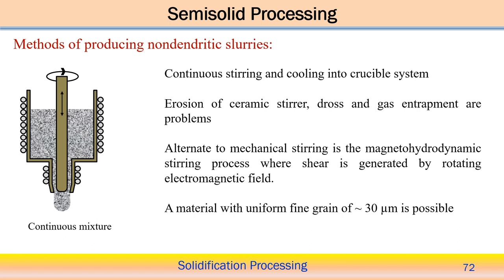Now, continuous mixing is possible in this case: pour the molten material, continuously mix it, and allow solidification to occur, along with the continuous stirring action within this container. And these are the cooling arrangements, a coil, so using this coil we can control the rate of cooling. So, with continuous stirring and cooling in a crucible system, we can produce the continuous mixture, or some kind of slurry. This is one of the techniques for semi-solid processing of a material.